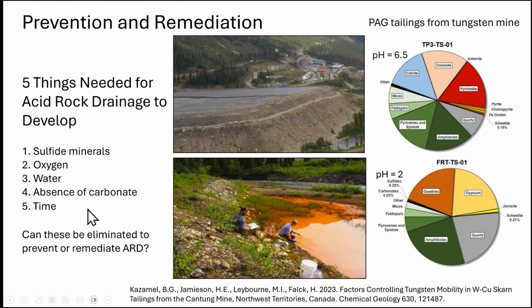And the rather frustrating thing is that this mining company that owned this deposit for a long time didn't spend a lot of money. They were a small company. They didn't spend a lot of money on environmental testing. So there was one kinetic test that was done in a lab, and it predicted that it would take 18 years before this material, no, actually, this is only about 12 years, but some of the other impounded tailings are 18 years. But one sample is not enough. So it's a tough one. But we think it's probably a combination of the limited oxygen and time.